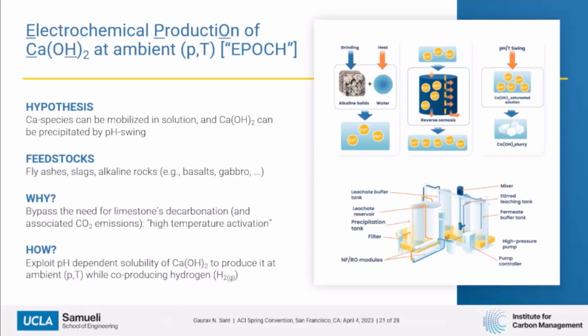Why is this important? If you could produce calcium hydroxide at a large enough scale with an approach of this sort, well, you can avoid the need for the high temperature activation of limestone, right? And then you can really switch towards using effectively a zero carbon feedstock for the production of cement. Keep in mind, these processes run at ambient temperature and ambient pressure. You're effectively just exploiting the pH dependent solubility of calcium hydroxide to produce it from solution, right? It comes out of solution at give or take pH 12.5, 12.7, and as I'll talk about in a second, you can do this while producing hydrogen if you use an electrolysis type of process.